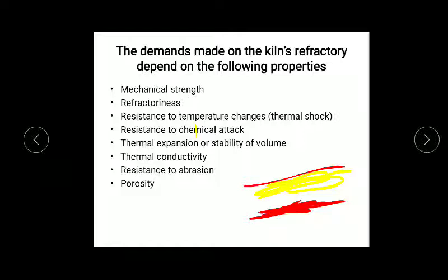So to decide on which refractory to use, you need to see these properties, like you have to see mechanical strength, as the material is being fed into the rotary kiln from some height. The material is fed from some height, and the refractories need to withstand that mechanical impact. Then refractoriness, since the rotary kiln is operating at very high temperature and there is certain amount of material which is lying on the refractories, the refractories need to withstand this high temperature plus high load, hence this is also important.